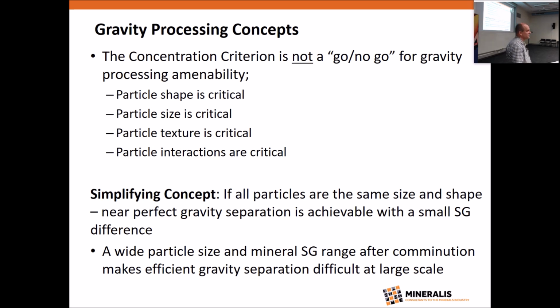So unfortunately the concentration criterion is not a definitive go or no-go for gravity. Size, shape and texture of the particles is critical, and it's rarely discussed in any detail in the textbooks, but the way the particles interact is very important. It's generally very specific to the type of equipment that's being used. And anyone who's ever tried to separate big flat plated gold particles from coarse material in a gold room will certainly attest to the annoying influence of shape.